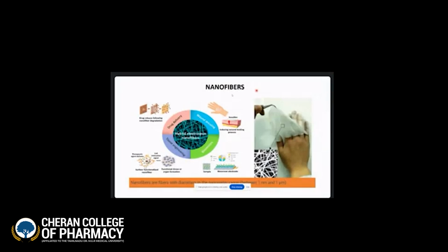We sent the sample for histopathological examination. From the examination we observed that the 2% alpha-mangostin nanofiber also shows fibroblasts and collagen, but the greater number of fibroblasts and collagen, and more follicle cells and epidermal cell growth, we observed in the 4% alpha-mangostin fiber mat.